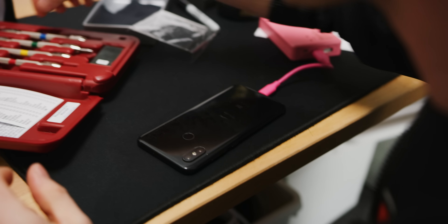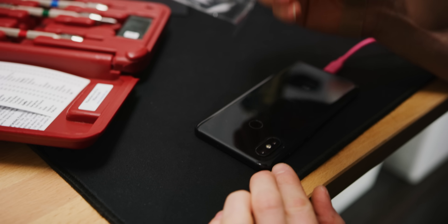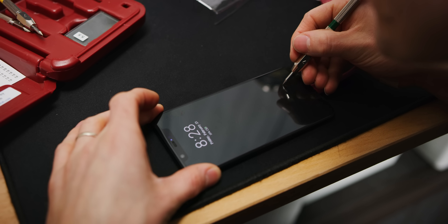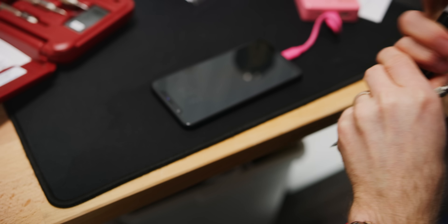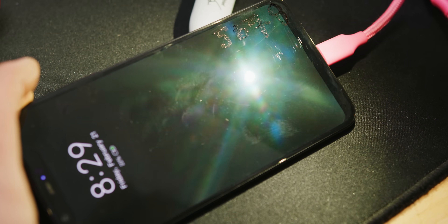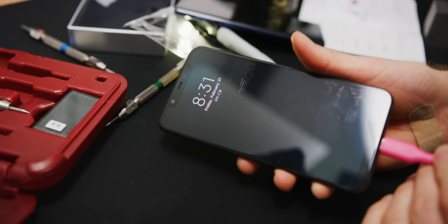Testing picks four, five, six, and seven on the ceramic coated side. The reason I'm retesting four is that I want to make sure the ceramic coating itself won't show surface scratches or imperfections — and so far it doesn't. At six, this is where the ceramic coating could separate itself. At seven, the behavior is basically identical to the uncoated side. Turning it up to eight — that's definitely more noticeable, but it still is better behaved when it's being scratched, not splintering apart like the other side did. On the ceramic coated side at eight, that looks basically identical to the other one.